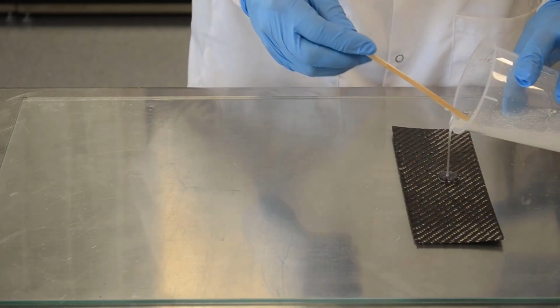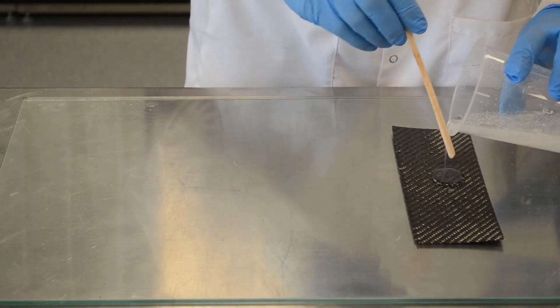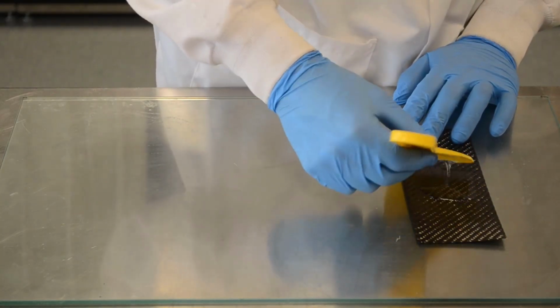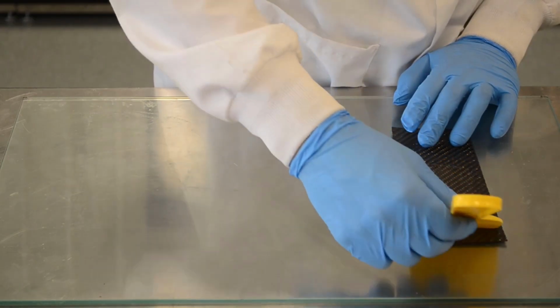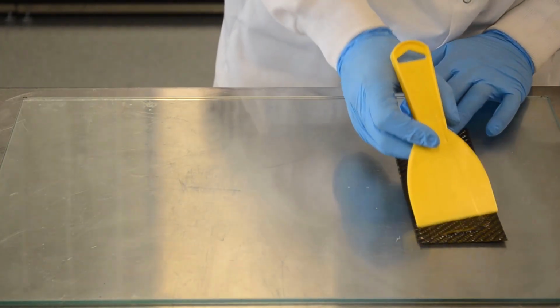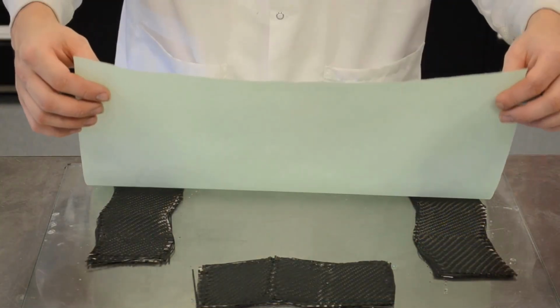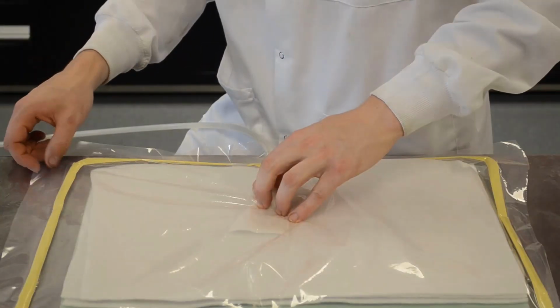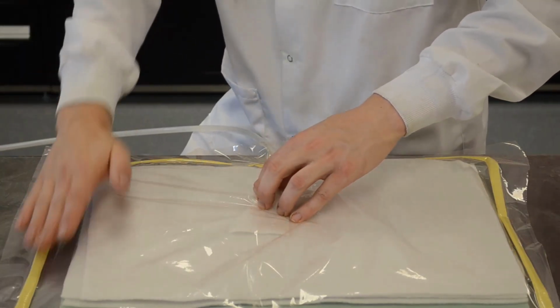Wet layup is a fabrication process where resin is manually mixed with dry fiber and placed on a single-sided mold, also known as the tool. This process is commonly performed without a vacuum bag, but vacuum bagging consumables can be placed over the layup to provide consolidation pressure and improve fiber volume fraction.